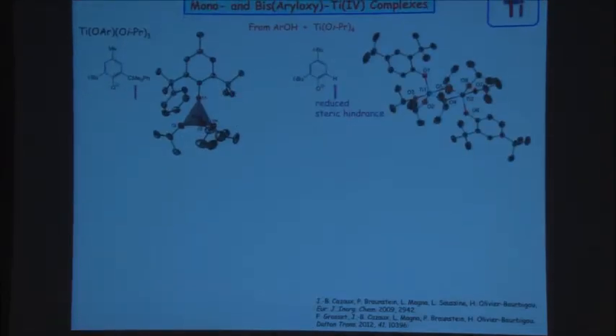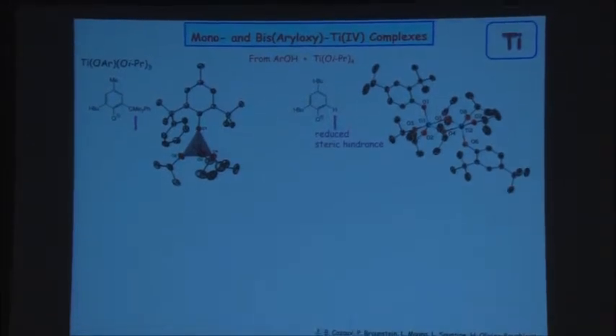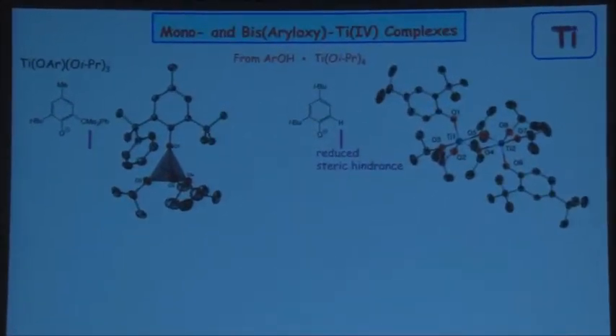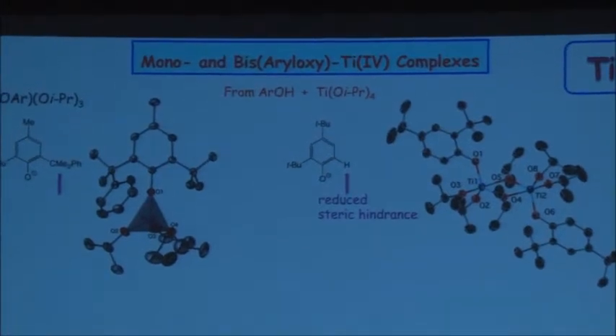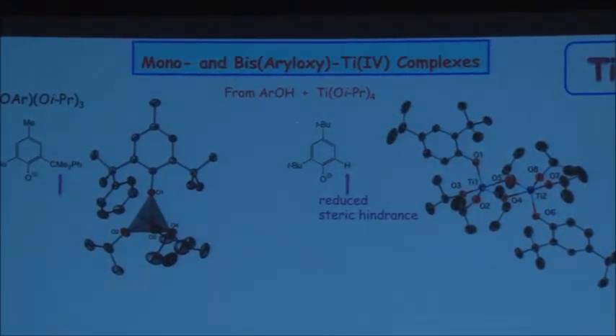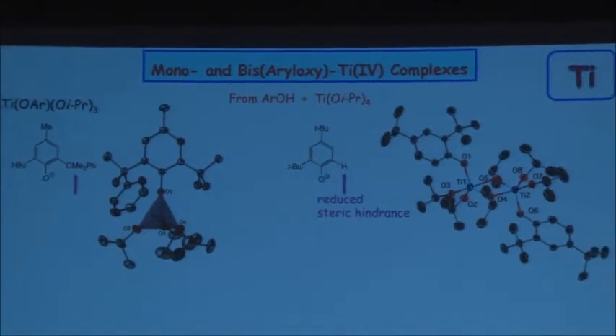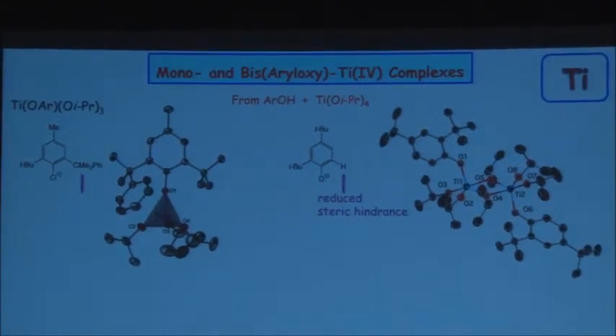Now let's apply this to titanium chemistry. Titanium, as I said, is a good catalyst in ethylene chemistry in many examples. We were interested to look at the chemistry of aryloxy titanium 4 compounds. And typically you will form them by reacting titanium isopropoxide with an OH group from an aryl derivative, and you will displace some of the isopropyl group in the form of isopropanol and incorporate your aryloxy moiety.